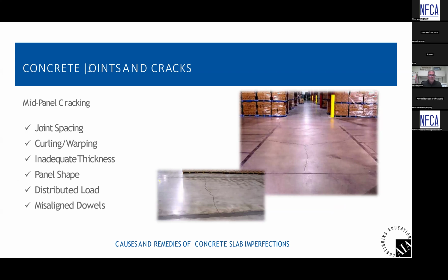Some of the other cracking that you can see out there, that we'll discuss, could be from a joint spacing standpoint. We did talk a little bit about curling or warping, and we'll show some examples there. It could be inadequate thickness of the concrete, panel shape, the load not being adequately distributed, and sometimes due to misaligned dowels when you're doweling one concrete pour to another concrete pour. The dowels that they use in both pours, that are epoxied into the core of both pours, may not be lined up right, and that could contribute to cracking.